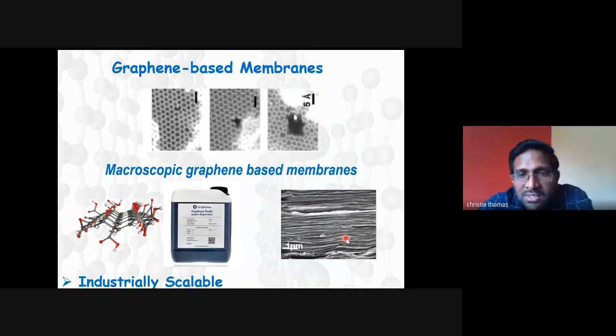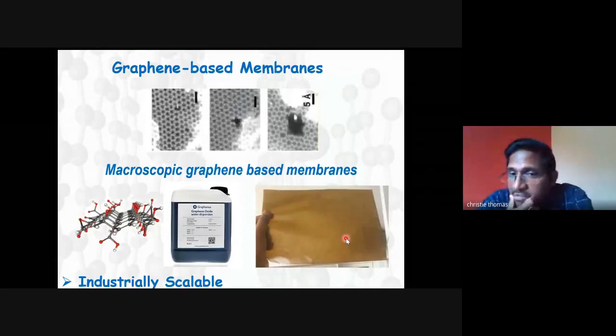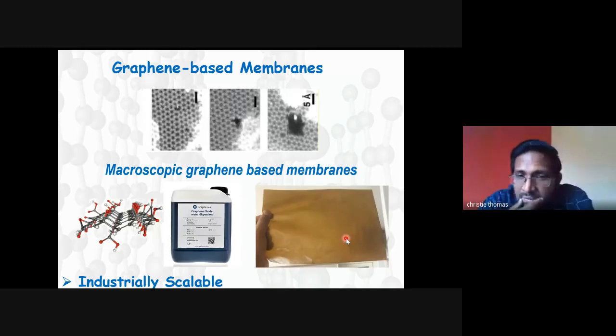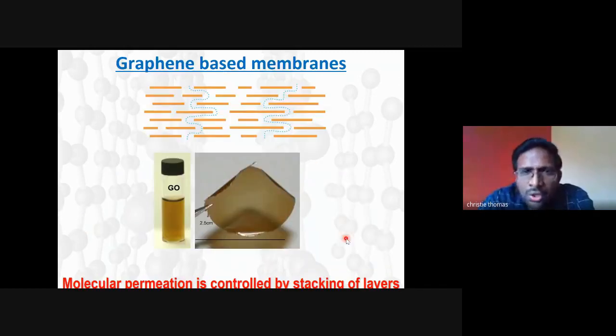So what are the advantages of this graphene membrane? It can be mass produced. This is graphene oxide coated on a sheet in an A4 size scale on a PET substrate. How can we make a graphene oxide membrane? It is very easy. If you have a GO solution, just drop cast it, evaporate it, and you will get an ordered stack of graphene oxide membrane, or you can vacuum filter it. You can spray coat it, or use the doctor blade technique. There are different methods. The most important point is the stacking of graphene sheets: atomically thin graphene oxide sheets stacked to form a proper membrane.